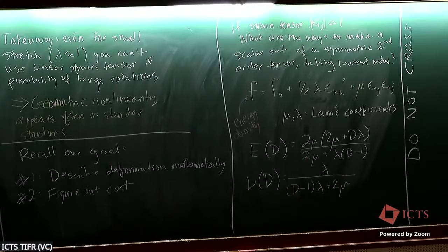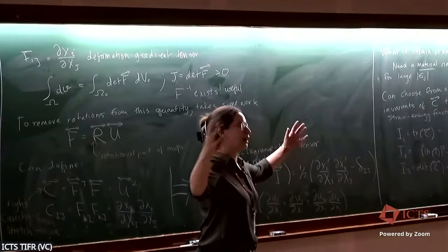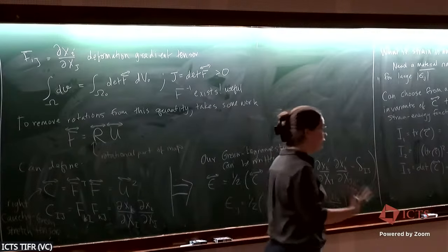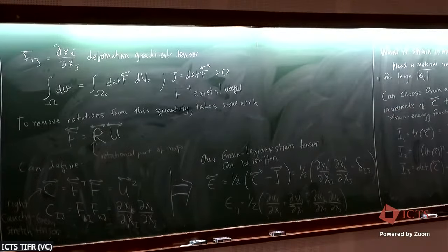Whereas these finite elasticity formulations will give you an infinite cost to take a large material and compress it down to a point. And that is something you actually see in a finite element simulation. When you know that your linear version is failing, you'll see one of these triangles just go to a point, and you'll think, oh wow, this really isn't the right energy functional. Yeah.